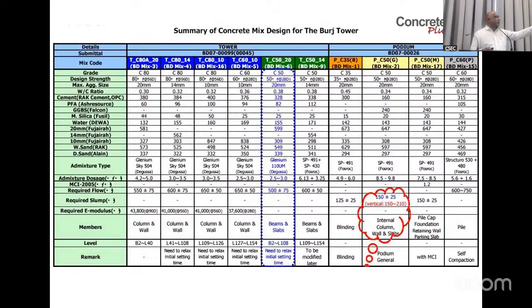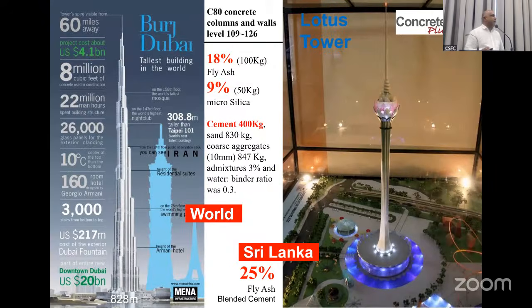So you can see the amount of admixture they have used is very high. Usually you use 1% of the cement weight in admixture, but here they have used up to 3%, 4%, sometimes even 7%. So even though I showed nicely that when you add fly ash, it flows up to 600 millimeters, it doesn't by itself. But with the admixture, together with the fly ash, it goes.